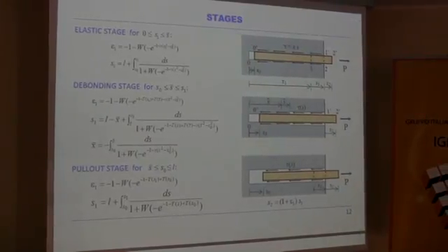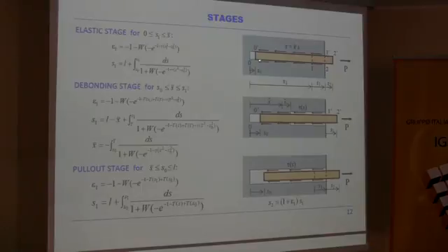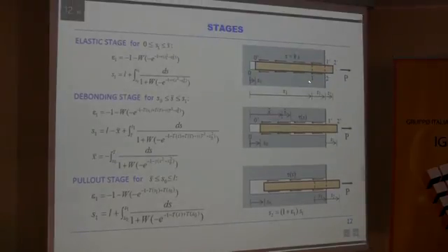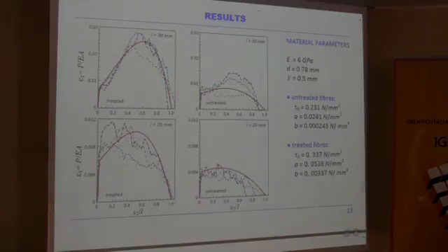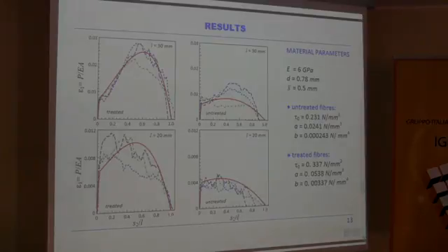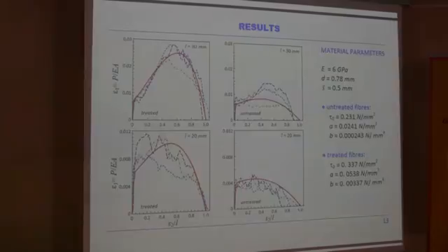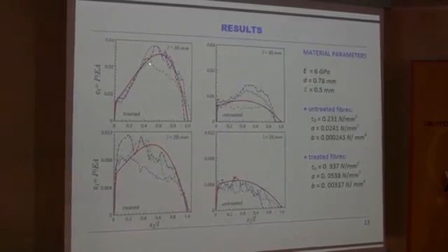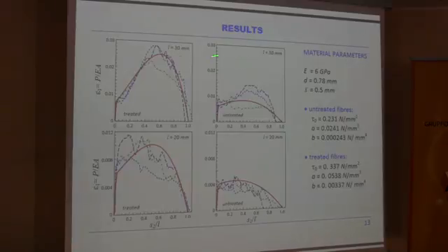Okay. So imposing the boundary conditions at both ends of the fiber, and at the section between the bonded and the debonded part of the fiber, we can obtain a closed form solution for each stage: for the elastic stage, for the debonding stage, for the final pull-out stage. We can obtain the relation between the pull-out load and the displacement of the fiber. And these are some results. We can see that the theoretical curves approach reasonably well the experimental results, both for treated and untreated fibers, and for both embedded lengths of 3 and 2 centimeters.